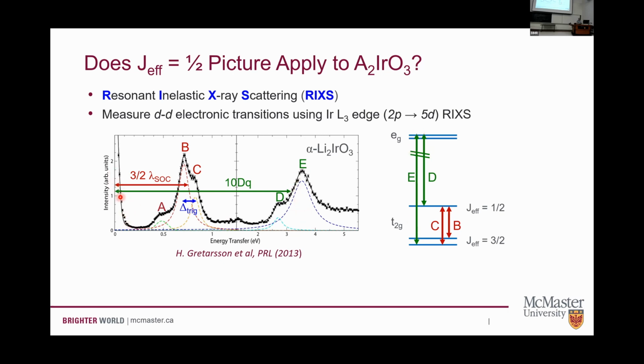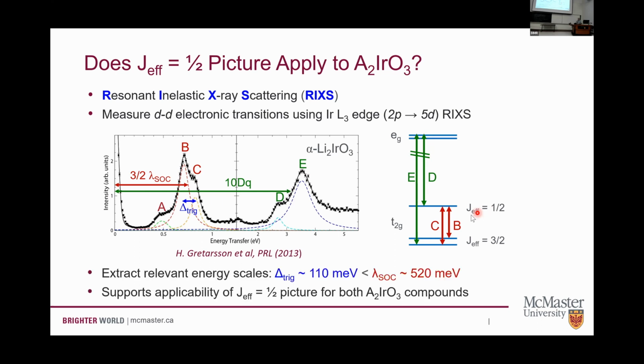The splitting between the elastic line and these features here tells us about the splitting between the J effective 3/2 and J effective 1/2 states. So we're mapping out the energies of these electron orbitals, and that lets us pull out the energy scales associated with the distortion of the IrO6 cage. That's this delta trigonal, the splitting that we see between the B and C peaks here, and the spin orbit coupling, which is the splitting between BC and A. Okay, and so the fact that this splitting is much bigger than this one is a good sign that this J effective 1/2 picture is still relevant, even though we don't have an ideal crystal structure.